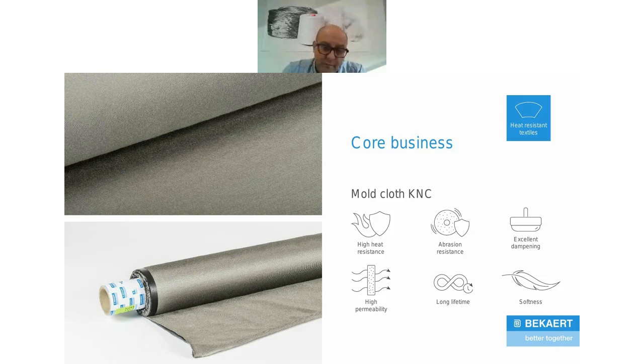And it should have a certain high air permeability. What do I mean by that? Because if you have the glass and the glass is bent, you have a certain vacuum that has to draw through the cloth, to pick the glass up to bend on the mold.